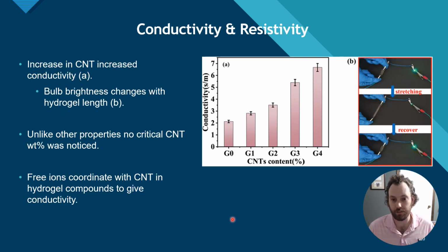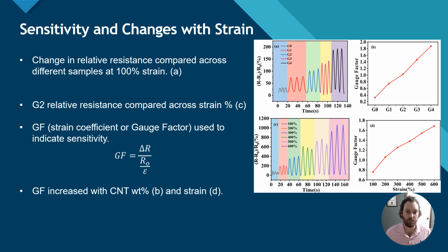That brings us to conductivity measuring itself. We first tested the conductivity across a 4-probe tester. We found that with increasing carbon nanotube content, conductivity increased. What you will notice is there appears to not be a critical carbon nanotube content like the elastic effects, so to speak. That being because the plasticity of the polymer did not contribute to the conductivity, only the free-flowing network of ions and their coordination with the carbon nanotubes, which explains why the conductivity increased with concentration and did not show a critical carbon nanotube content. With a known conductive polymer here, we decided to move on to resistivity testing and sensitivity.